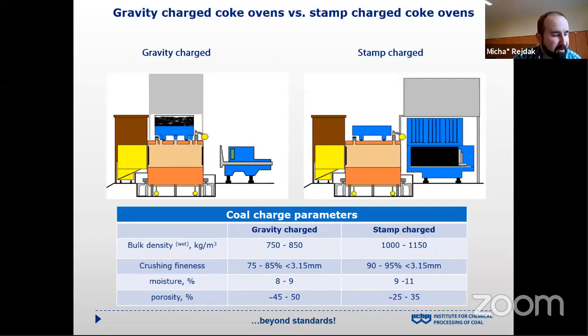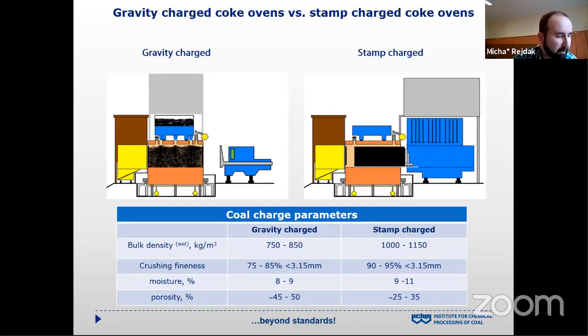In the case of gravity charged battery, the coal blend is gravity charged into the coking chamber from the top of the battery through the charging holes located in the battery roof. In the case of stamp charged battery, the coal charge is first compacted in a steel box by a row of stampers, and in the form of stamped coal cake, it is pushed into the oven chamber through oven doors, which are located on the machine side of the coke oven battery.